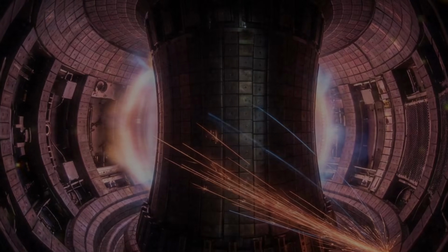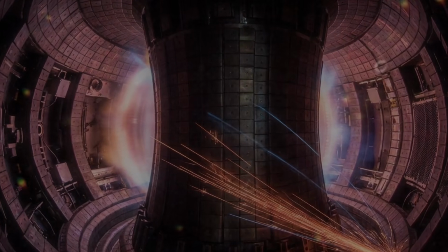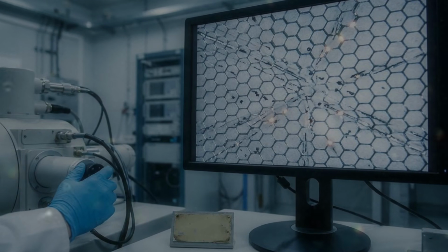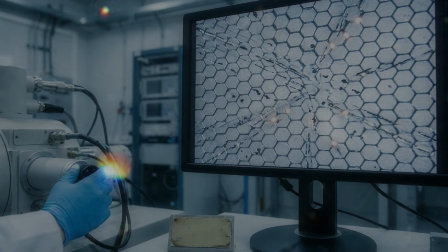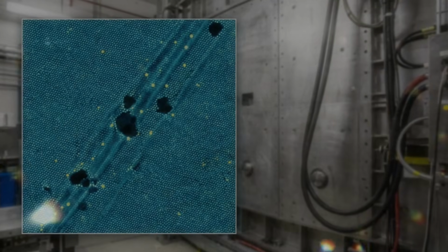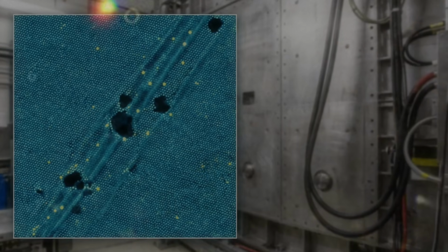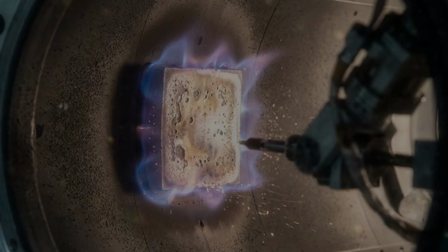Boron also illustrates something important about plasma-facing surfaces. Sometimes the best surface is not the bulk material underneath. A wall may be made from tungsten, steel, or another structural material, while the plasma actually interacts with a thin modified layer. That layer can change the chemical behavior of the edge, reduce impurities, and improve plasma conditions. The wall becomes more like a carefully prepared interface than a simple slab. It is not only what the wall is made of, but what the topmost atoms are doing today, after yesterday's plasma exposure, after the last conditioning cycle, after the previous burst of heat. In fusion, even the surface has a memory.